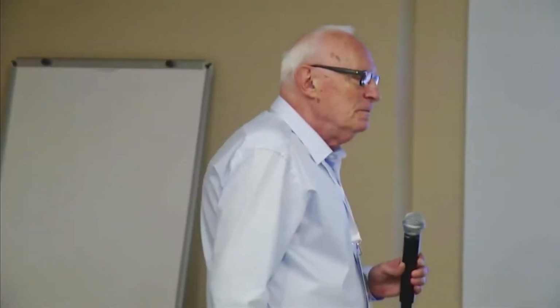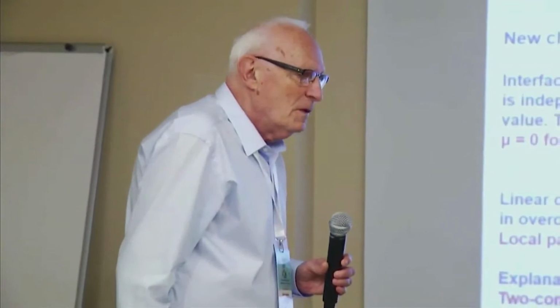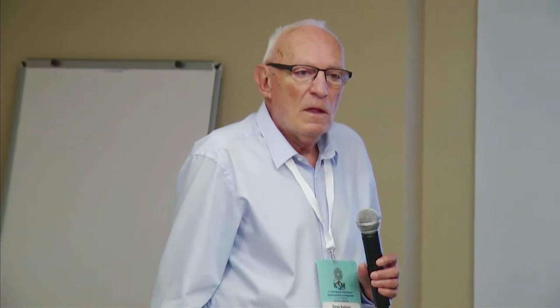So I would like to ask you, in cuprates, it was shown that the Fermi velocity is more or less compound and doping independent, down to very low doping, up to high doping. How do you reconcile that with your story about the chemical potential?